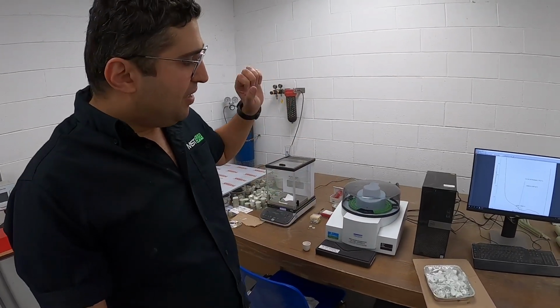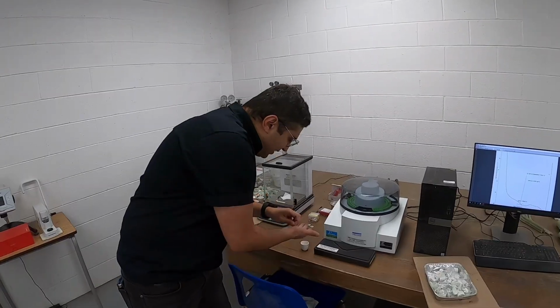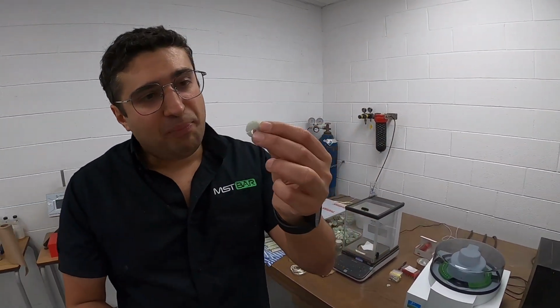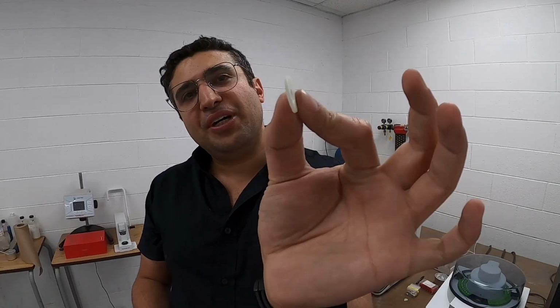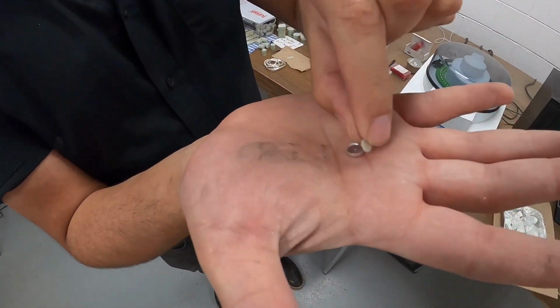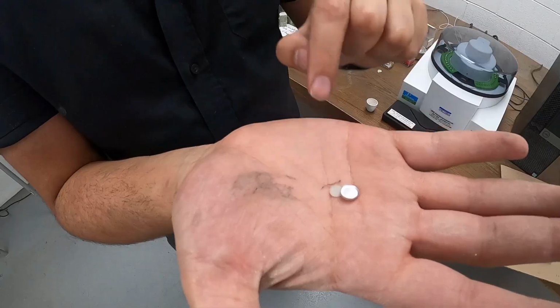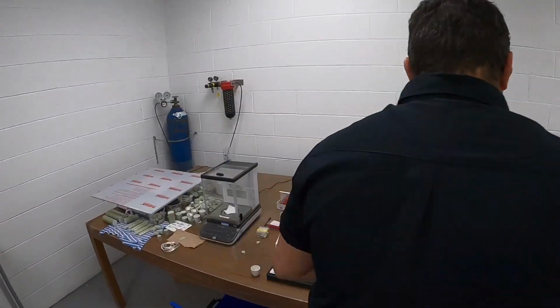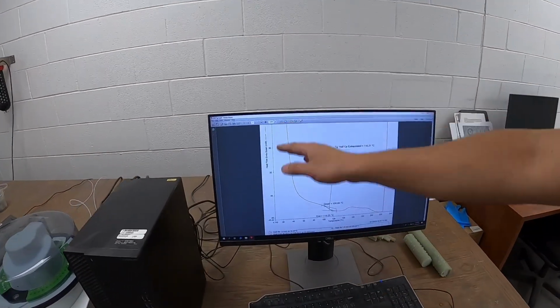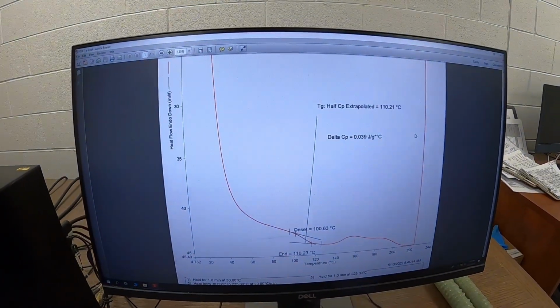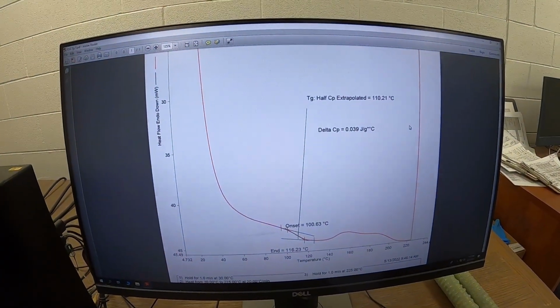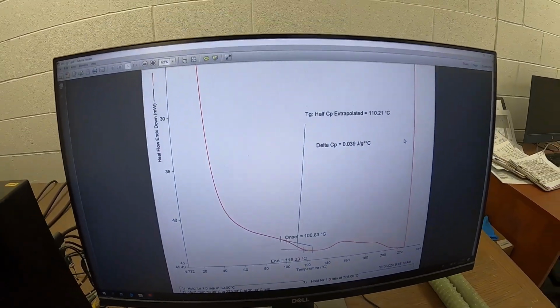Matt, the other machine we have is a DSC machine. We grab a piece of rebar, we punch a little hole in there, and you can see how tiny this is, and we place this little piece inside this capsule, seal the capsule, and place it in this machine. This machine is going to run from room temperature to about 600 degrees Fahrenheit and draw you a chart. This chart will tell you where the Tg is and how well that polymer is crystallized, how well this material is cooked, the recipe. So it basically proves that your recipe has been perfect.